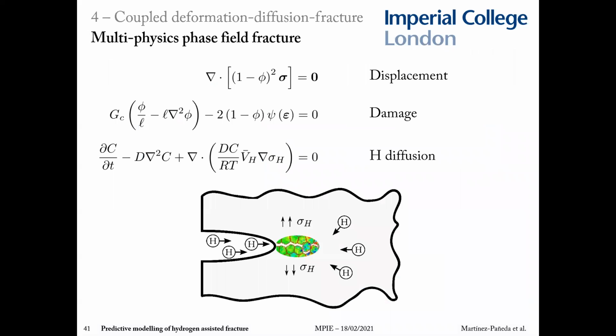So how does hydrogen come into the picture? Well, let me remind you of the three balance equations. There's one for the displacement field, with the phase field degrading the stiffness of the solid like a damage variable. There's one phase field evolution law, which is sort of a competition between the strain energy density of the solid, which changes with the strain state, and the fracture energy. So whenever you have enough energy stored in your solid, your crack will grow. That's consistent with thermodynamics. And then you have a hydrogen transport equation with hydrostatic stresses driving diffusion.